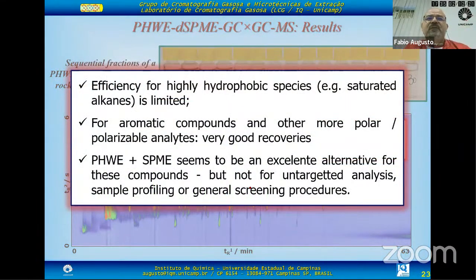We found this combination is not very efficient for highly hydrophobic species such as saturated hydrocarbons. Obviously, it is better for aromatic compounds and other less hydrophobic compounds. It seems to be an excellent alternative for these compounds, but not for general, non-target analysis. Right now, we are studying combinations of ethanol and water mixtures, and blends of methanol and water. The results are very promising, and we are applying it to other compounds and other samples, such as plant samples and so forth, with very interesting results. But of course, hot water, subcritical water, is much more adequate for aromatics.